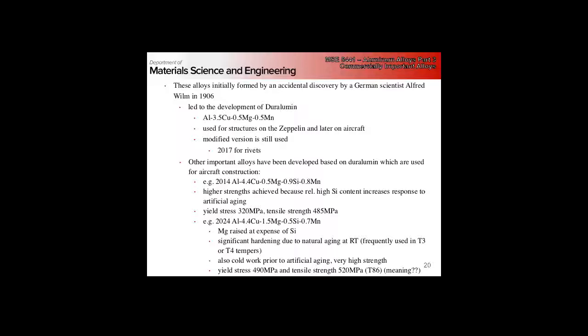2024, which is a really popular aerospace alloy starting around the time of World War II, we raise the magnesium and reduce the silicon. This allows us to get more significant hardening at natural aging at room temperature.